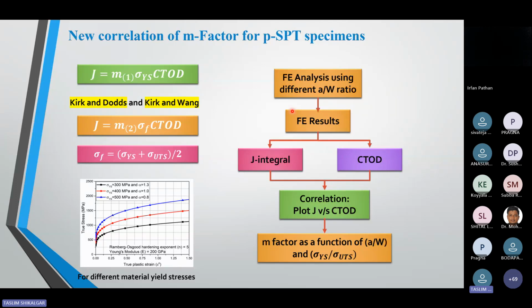So with the help of the FE simulations I generated results, that is the load displacement data, and from these FE results I used one code to find the CTOD. So I got the CTOD from these FE results. But this is the J integral, and to calculate the J integral, all commercial softwares have the J integral approach incorporated, so easily you can get the J integral, which is path independent. So I calculated the J integral for each specimen ahead of the crack tip, and I plotted J integral versus CTOD. And I observed that I am getting a linear correlation between the J integral and CTOD.